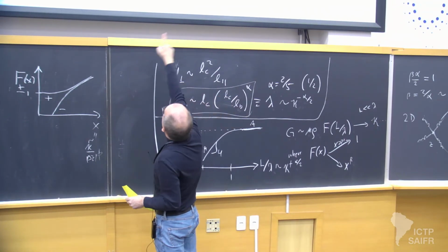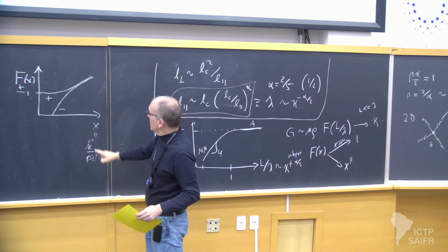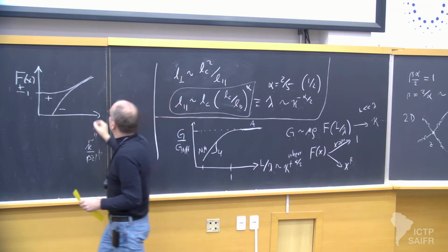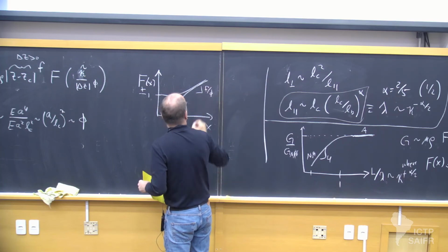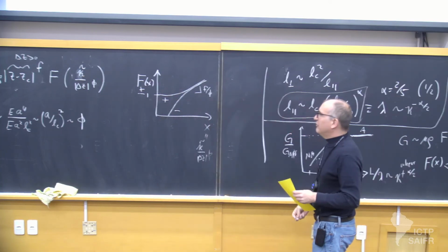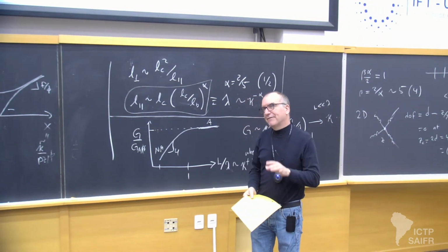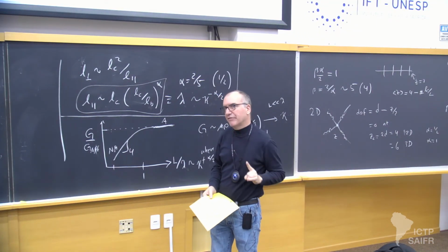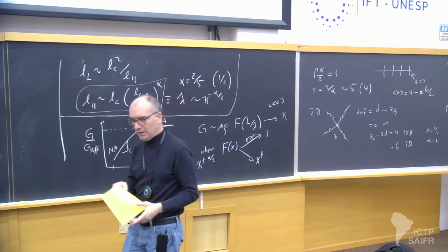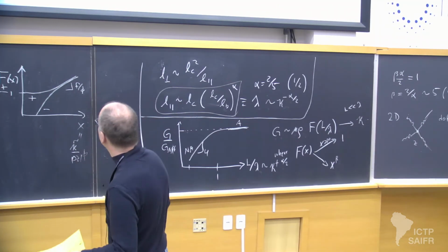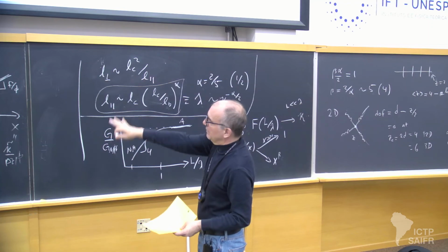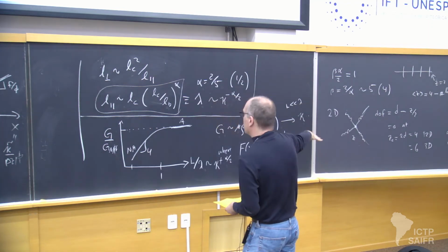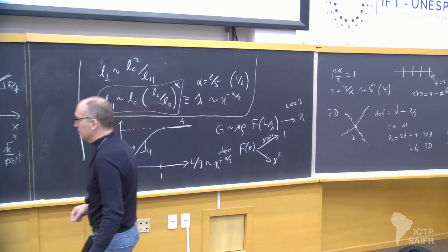And so that function on the right basically shows you these, okay? With a slope in between, which is the ratio of f to phi. Mean field suggests that should be a half. Simulations show it slightly different from a half. Again, non-mean field, maybe shouldn't be too surprised. Okay, so that was a fun little extension, if you like, of these Maxwell argument ideas to include bending.